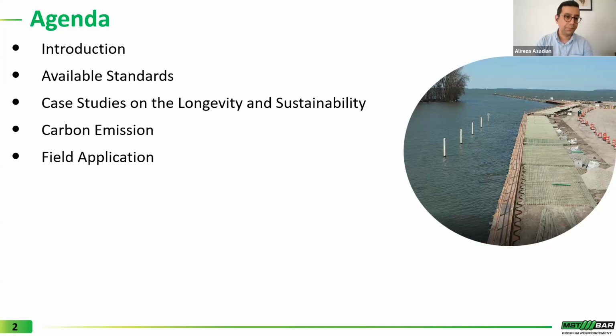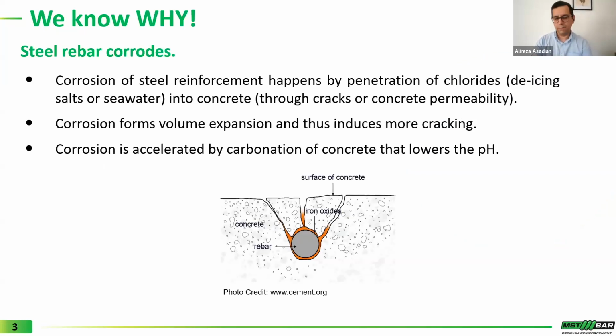So as you may have seen in your everyday commute, our infrastructures, buildings, bridges are suffering from corrosion of reinforcement. Corrosion happens by penetration of chloride into concrete. Corrosion forms the volume expansion of the rebar and can induce more cracking, cover spalling, and exposure of internal reinforcement to aggressive environmental conditions. Also, it's important to know that corrosion is accelerated by carbonation of concrete that lowers the pH environment of the rebar.